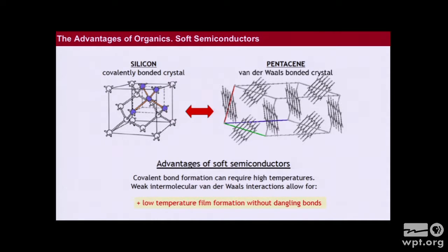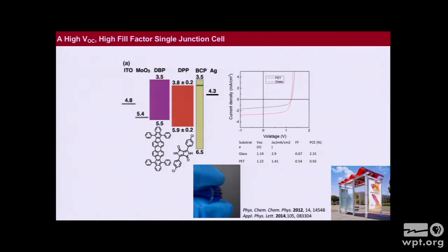The disadvantage is that since it's a weaker bond, you actually have higher resistivity or lower conductivity in these systems. But because this is a weaker bond, you can actually make these films on absolutely anything at room temperature. Okay? And so obviously it's the advantage that we're going to take use of in order to make solar fabrics. So you can make a ton of flexible devices.